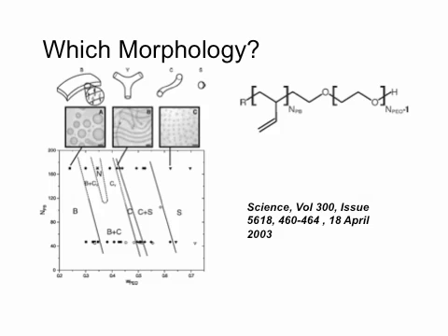So if I now make that bit shorter and shorter, so I go to the left, I should up my packing parameter. So I go from values that are less than a third to a half and eventually to 1, which means that my assembled structures should change from spherical micelles to slightly eggy things, elongate into cylinders, and then in the end will form bilayer sheets or vesicles. And that's exactly what you see. So by playing with the relative block length of these things, you can tailor what type of structure you're going to get.